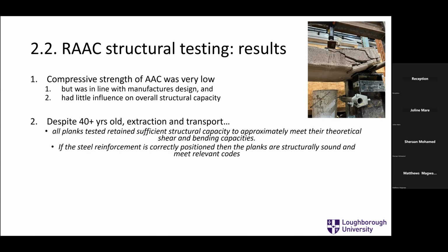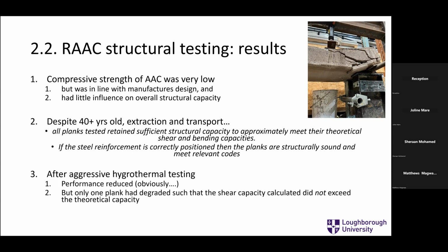And one of our conclusions, we tested 40-year-old planks. We took them out of buildings, we transported them on the motorway, we craned them in the lab. They cracked a lot. They do crack quite easily. And we tested them. And even then, they took a good bending moment above what they're meant to from the design codes. So again, the planks themselves aren't too bad.